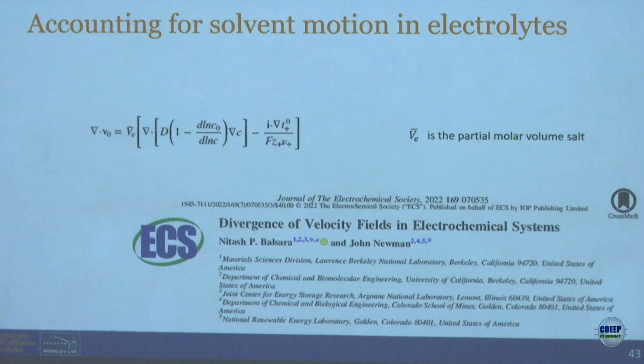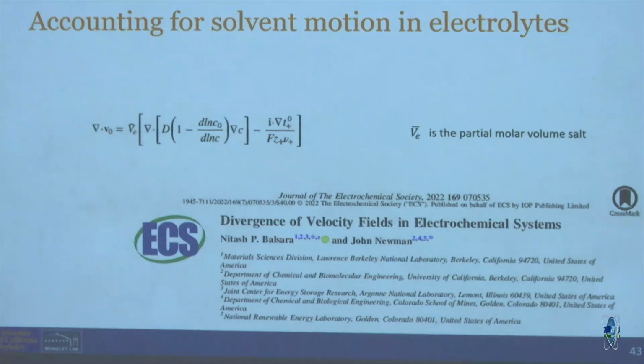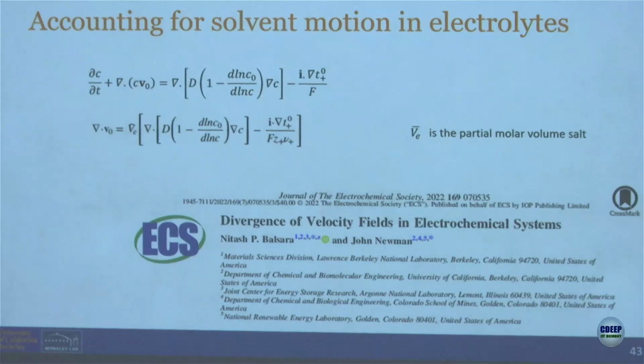But the prefactor is the partial molar volume of the salt, which, if you think about thermodynamics, is never 0. So you add salt, the volume has to change, either up or down, usually up. Actually, usually down. Anyway, it's always some complex function of concentration which we can measure. Using that, we can then go to town. Now we have a complete set of equations, and we can determine concentration and solvent velocity as a function of space and time.